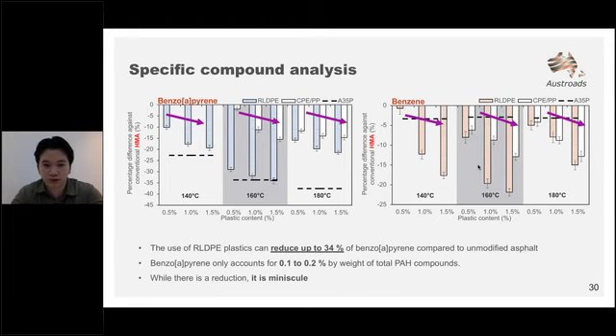So although the levels were decreased by 15% as I mentioned earlier, it sits on a different scale of magnitude when compared to the current threshold. Essentially, what we're getting is about 2 to 8 micrograms per cubic meter, which is the measured concentration, versus the workplace threshold of 200 micrograms per cubic meter over a 15-minute period for benzene.